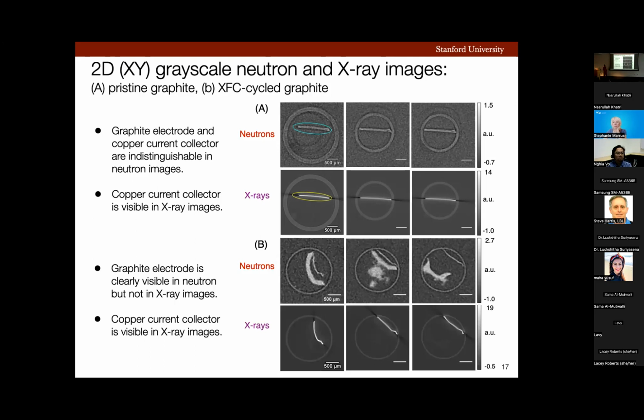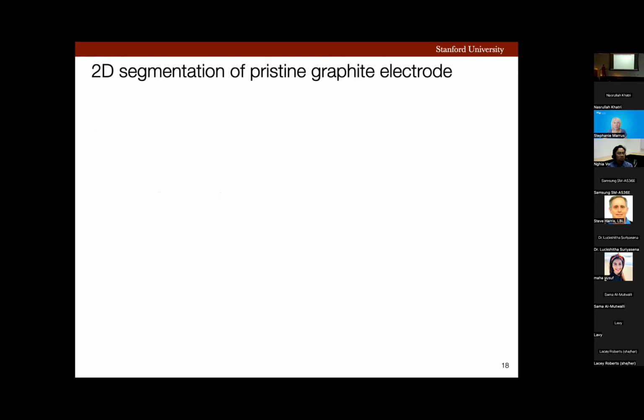Now let's look at the data for the XFC cycled electrode. Here we are looking at the outer glass capillary as well, and then we are looking at this graphite anode, which is clearly visible in the neutron images, but not so in the X-ray data. In the X-ray data, again, we can see copper pretty clearly. Thus, we can use the information from this neutron and X-ray image to create a two-dimensional histogram for an improved segmentation, which I'll show you on the next slide.